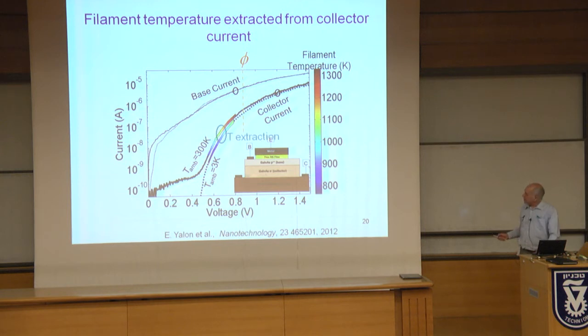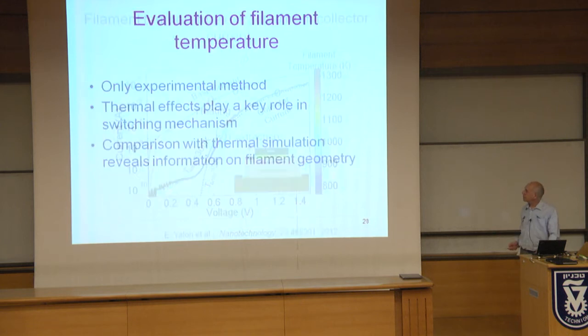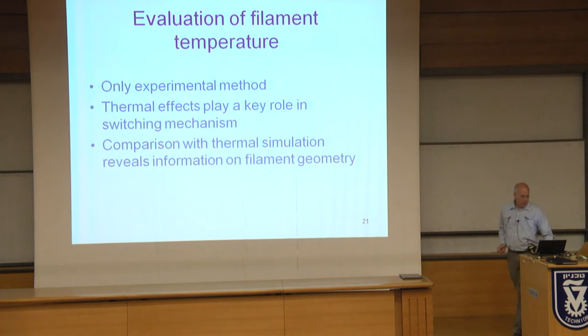This temperature is extracted from the collector current at this region of the IV curve, and this is actually caused by the heat from the base current, which is much larger in this range. Okay, so we believe it's the only experimental method which is available nowadays to evaluate the filament temperature. We're not aware of any other methods, at least for small oxygen filaments.